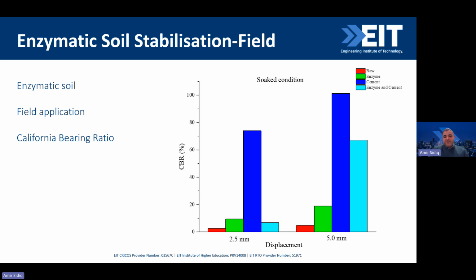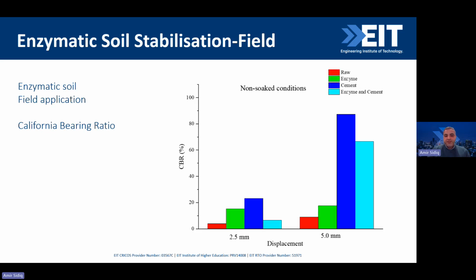Similarly, we had it for the non-soak conditions. The CBR is generally taken for the soak conditions. However, I wanted to know what is the scenario for the non-soak conditions, and I just wanted to know is there going to be any changes or not change at all? Seemingly, there's not much changes. I mean, there's a slight variation for the raw and for the enzyme, but it's not significant.